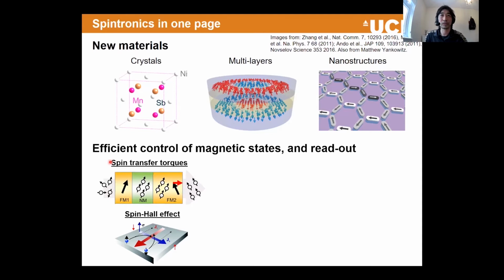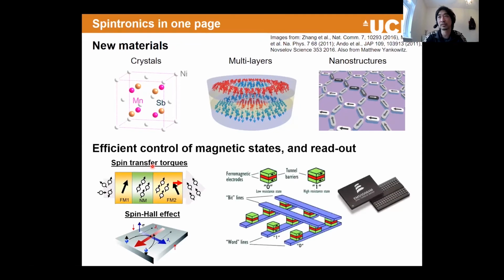And that's what we call spin transfer torque. Also, the creation of this spin polarized current can be done through the so-called spin Hall effect, which originates from spin orbit interaction in the materials. These two effects can switch magnetic materials by electric current, for example. If we do this very efficiently, we can foresee making highly efficient memory devices.